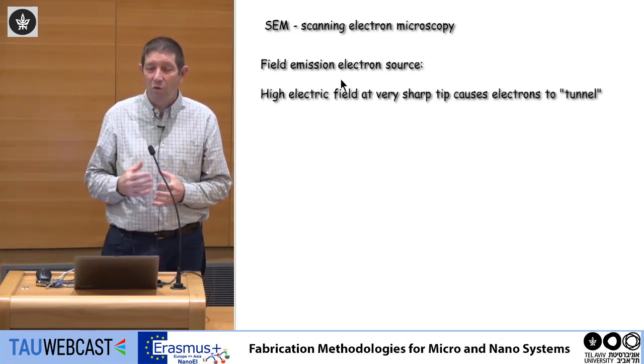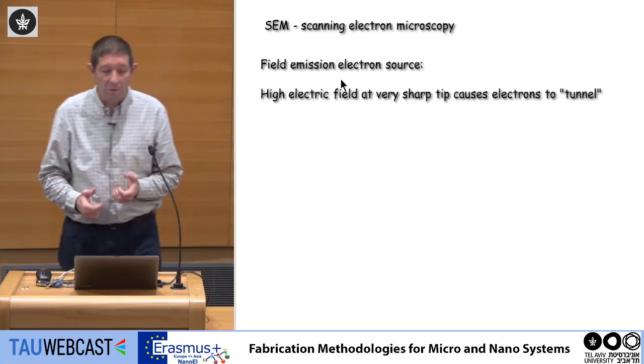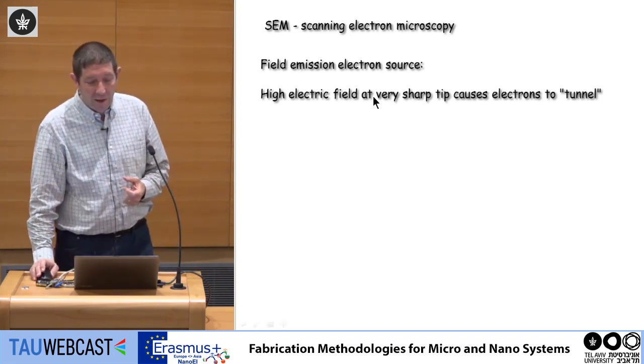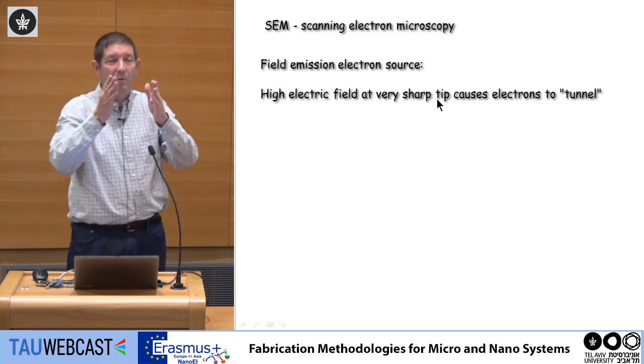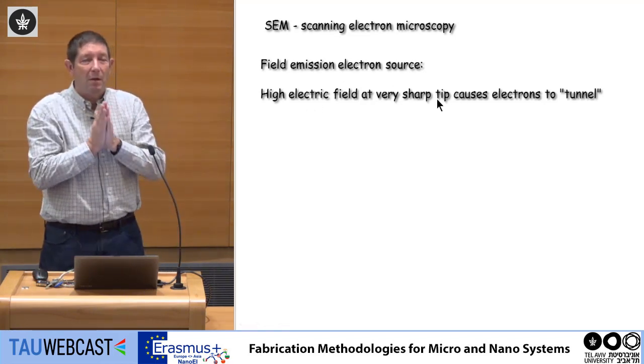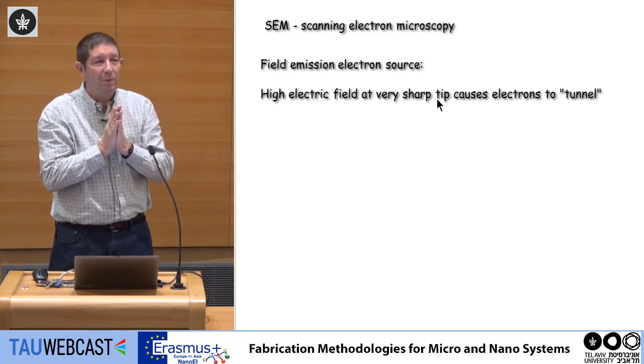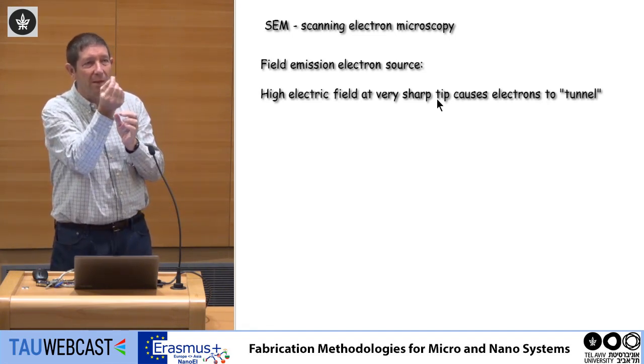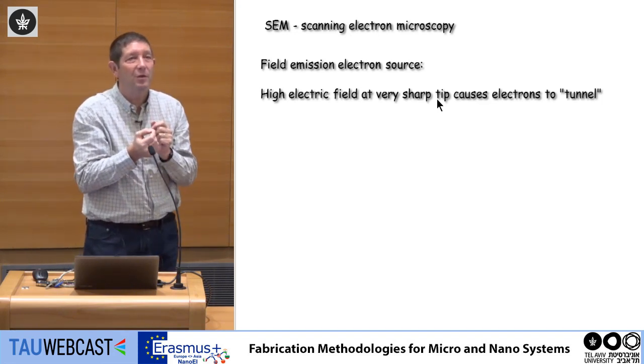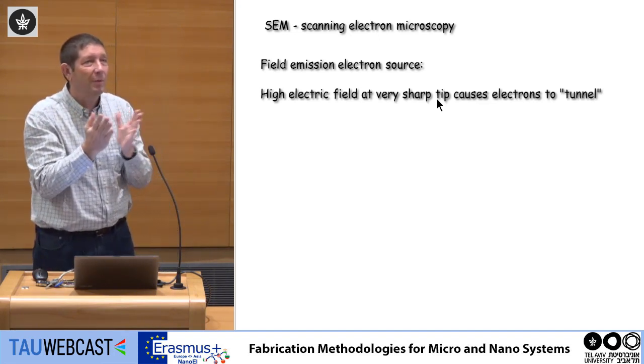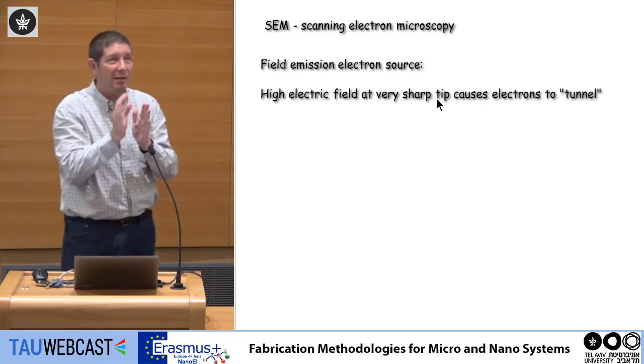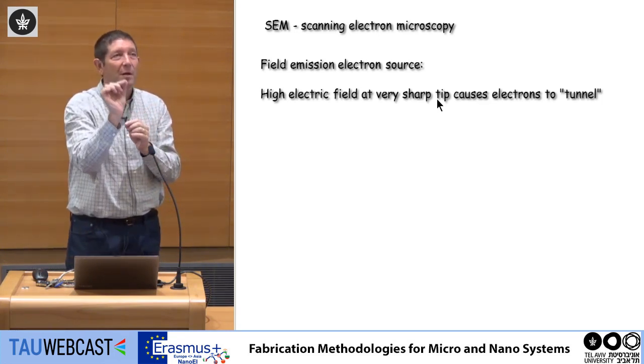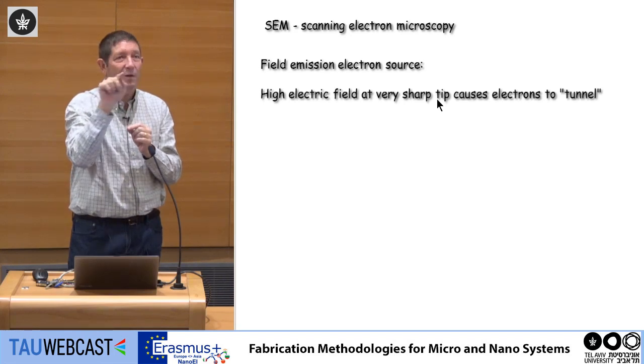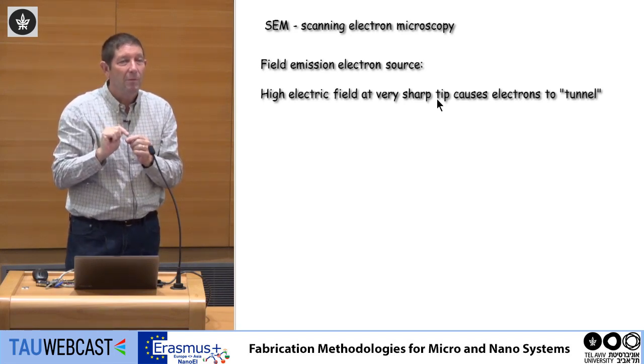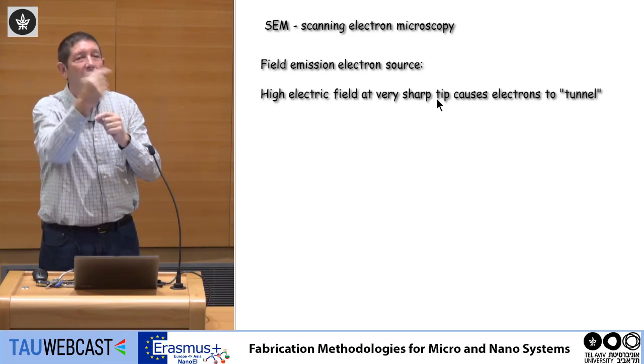We have less resolution, and the field emission guns have higher resolution, and it's used to generate a high electric field because we use a very sharp tip. If you have a very sharp tip and you apply voltage next to the tip, you have a very high electric field. I hope you remember from electrostatics that next to a tip, the electric field is proportional to the voltage divided by the radius of the tip. So the sharper the tip, the larger the electric field.